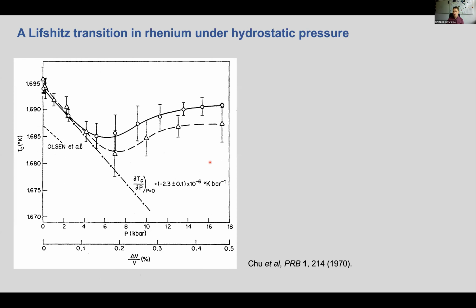A similar experiment was done on rhenium. So this is rhenium under hydrostatic stress, and its TC initially has this stress linear decrease, but then starting at about half a GPa, there's an anomalous increase in TC, and that is also associated with a Lifshitz transition. The scale of the change is tiny. TC drops and then goes back up by something on the order of 10 millikelvin, less than 1% of the unstressed TC.